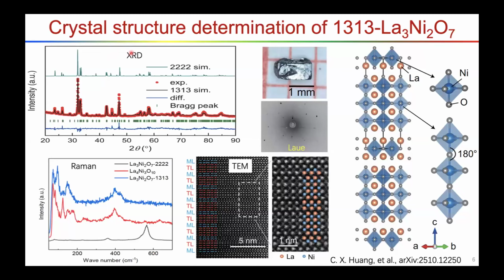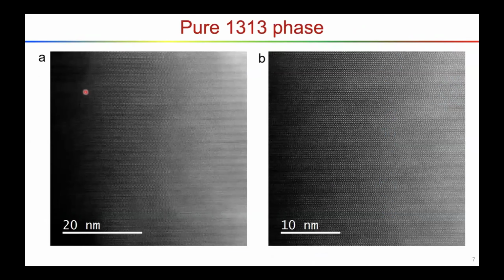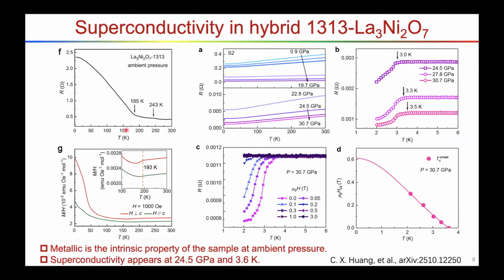As you can see from this XRD measurement, this is the bilayer phase position, so we couldn't see the bilayer phase. And we can use the TEM to scan a very large scale. This is 20 nanometers. They are all this 1313 phase. That means our sample is a pure phase, and it's very high quality. Okay, on this sample, we conducted transport measurements.